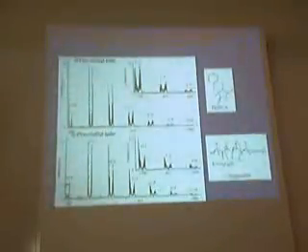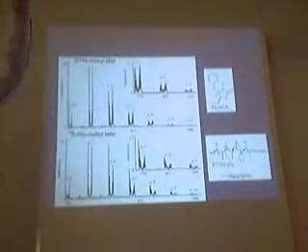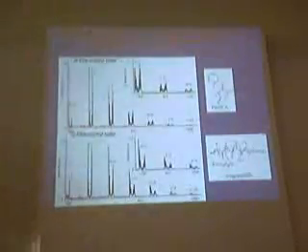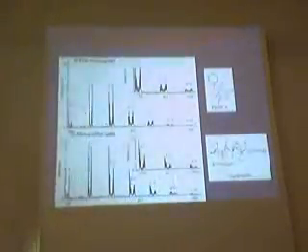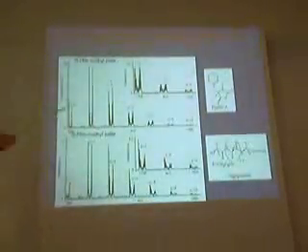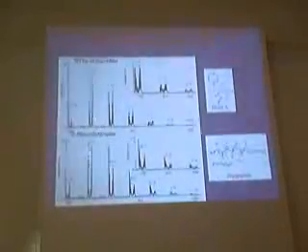In the tetramer, we see that the S is formed in excess, but as we move to the 6 and the 7 and the 8 and the 9, there is a reversal. This reversal in the enantiomeric excess is in keeping with the formation of the racemic beta sheet. Now, the reason why I mentioned that experiment is that I thought, if this is the mechanism by which the reaction can operate, then why do this in a crystal? You can go in water.